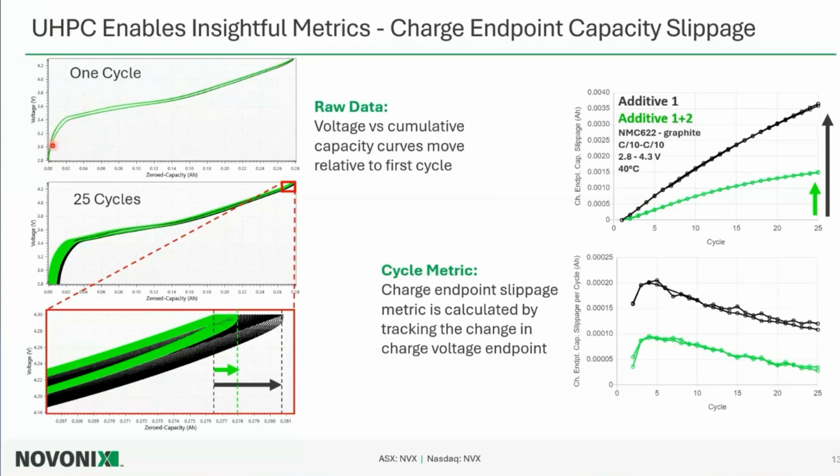And then during discharge, we're not going to count all of those electrons again. So we're going to miss out on counting them because they are self-discharge mechanisms. So we're not going to end back at 0. The subsequent cycle, we're going to count more electrons than that previous discharge because we're going to count a lot of those slippage-based mechanisms again. So what this looks like in a lot of cases is over many cycles, our voltage curve kind of shifts to higher and higher capacity because we're overcounting electrons during charge and then not catching them on discharge.